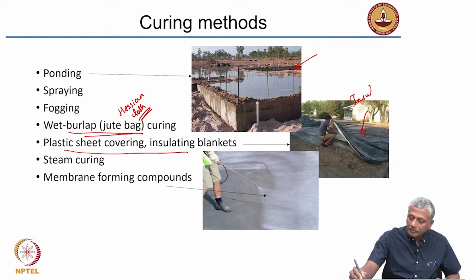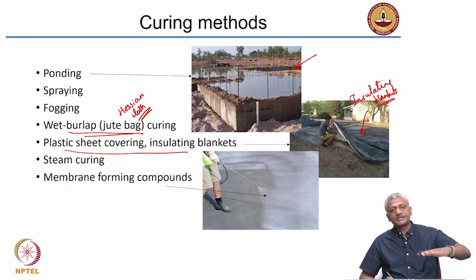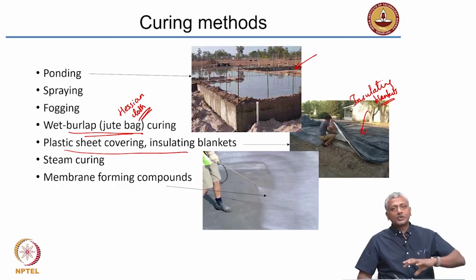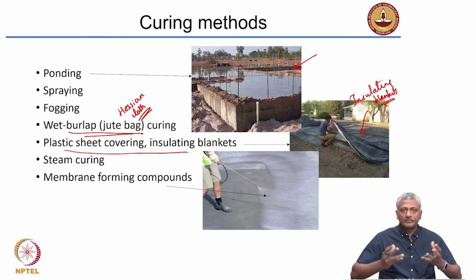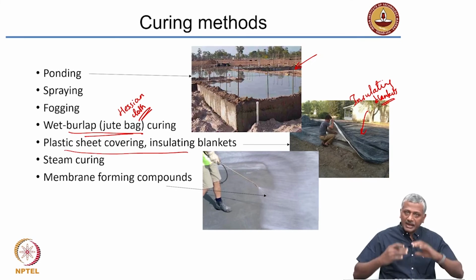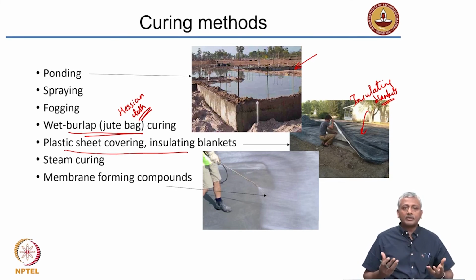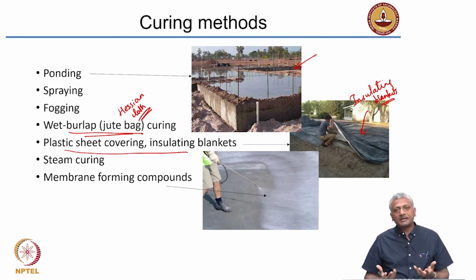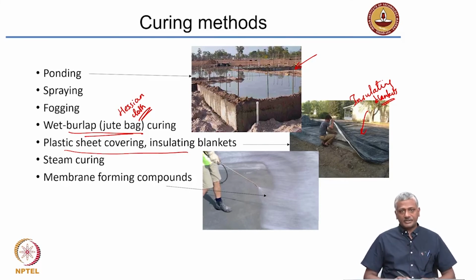Insulating blankets. Now, why do you need insulating blankets? Insulating blankets not only cover the surface and prevent water evaporation, they also ensure that the heat generated because of the hydration is kept inside. And why is that important? Because when the heat is maintained inside, it will lead to a faster hydration of the concrete. It will speed up the reaction rate, which will cause the attainment of strength much faster. So insulating blankets are used very often in cold weather concreting.